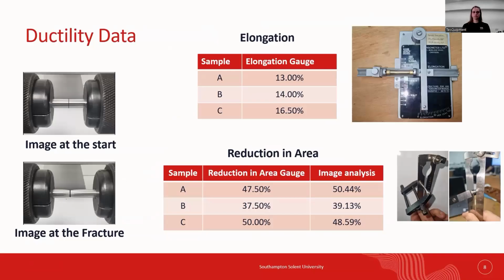Initially, we struggled to measure the elongation and reduction in cross-sectional area of fractured samples with a caliper, as we need to reassemble them. To rectify this, we used two alternative methods. The first method was image analysis to calculate the reduction in area. We used the images captured during tensile testing and, using a known measurement, captured the pixels per millimeter and applied that scale to the unknown measurement. This was more accurate. The second method was using analog gauges. The gauges are pictured on the right, and it was found that the elongation gauge was more precise for measuring elongation. However, image analysis was more accurate for measuring reduction in cross-sectional area.